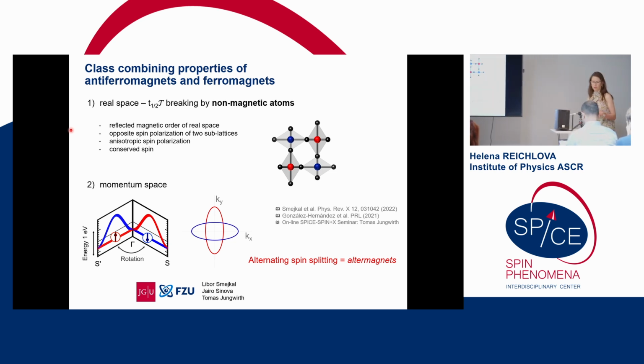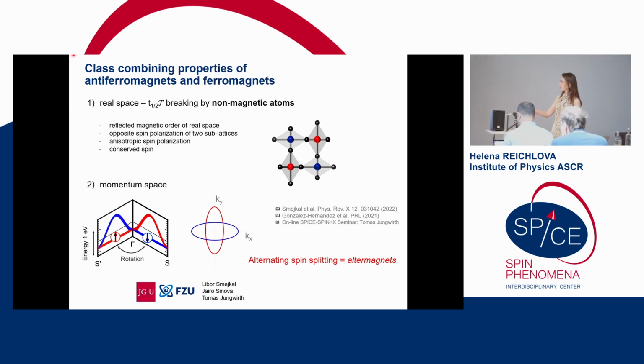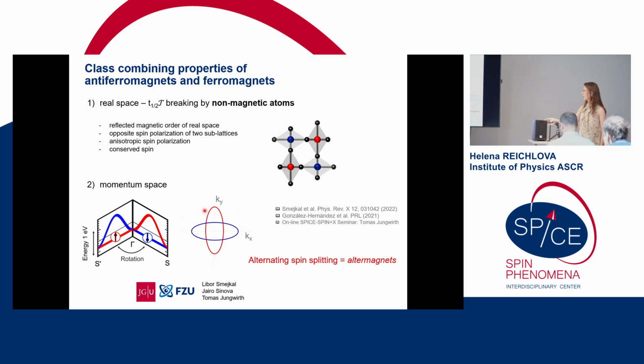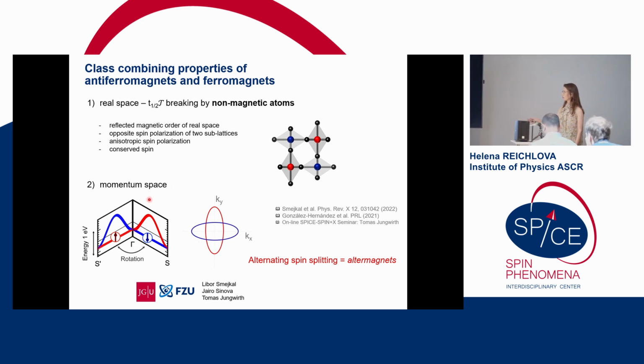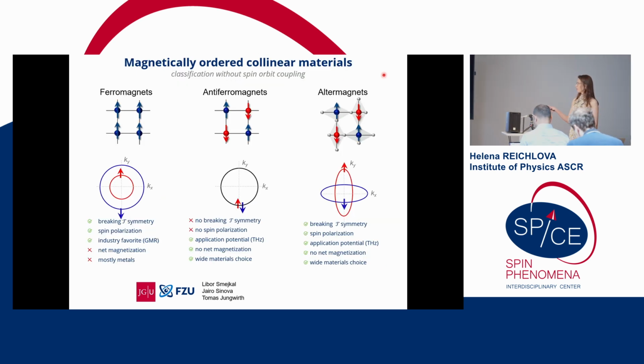But what is important for spintronic research is that these energy cuts, which I was showing before, are now not degenerate anymore, and depending on the crystal direction, we can see that there will be an excess of spins up or spin down, leading to all these effects which rely on the spin polarization. So coming back to this table, we see that the altermagnets combine the properties of the ferromagnets and antiferromagnets, and on top of that, they have this characteristic anisotropy, which is unprecedented in the ferromagnets and antiferromagnets. So this is the very brief summary, also of what you learned from Matthias already.